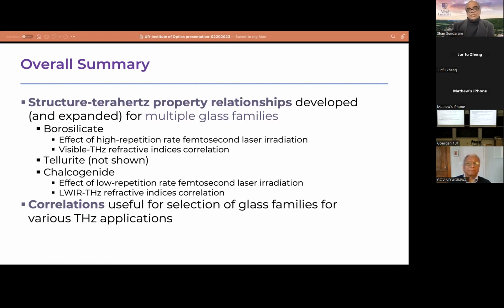So the big picture is we have actually put together what we call glass structure and terahertz properties. At least for these 3 families, we have shown what are the structural units present in these glasses and how they affect the terahertz properties we are measuring. And we also found simple correlations like refractive index or absorption to refractive index in other frequencies like the visible range or long wave IR range for chalcogenide glasses. And these correlations will not only help you to select one family of glass to do maybe several functionalities in various frequency regions, and by looking at what range you want to cover.